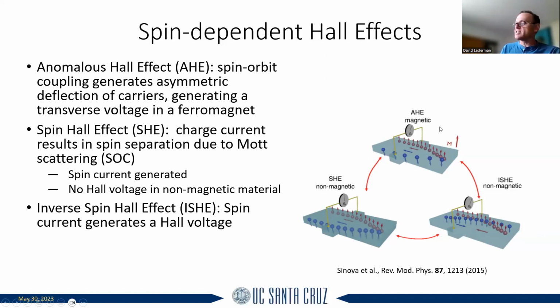Okay. So these are three important effects, right? And in this case, the electric field is perpendicular to the spin current and the magnetization. So you can see the spin current points to the right, you end up with a voltage like this, that's perpendicular to both the spins, sigma, and the spin current. Okay.